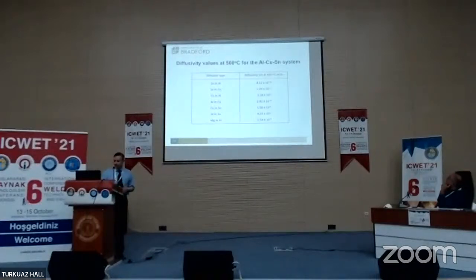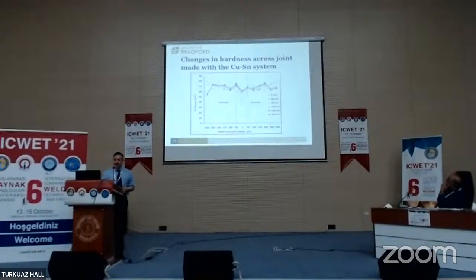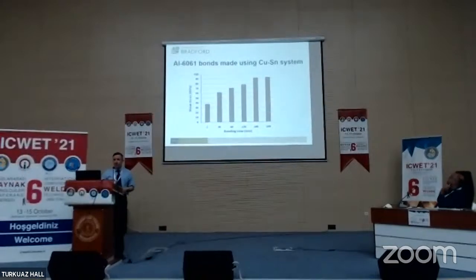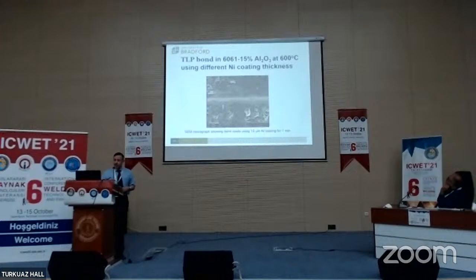diffusion into the joint. And if we look at the hardness profile, now we do not get a very high hardness in the middle, but an undulation in hardness values. And this is shown in the joint strengths as well. So right in the initial stages, if we look at the shear strength of the joint region, then for 2 minutes, it's the lowest. But if you look at the longer bonding times, we can actually regain that strength as well.